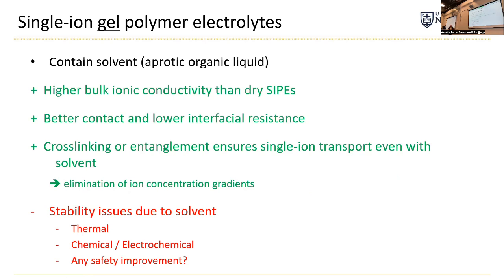Okay, so what I'll tell you more about today is our recent work on single ion conducting gel polymer electrolytes. The previous slide was about polymers where there are no liquids, it's just the plastic, and those suffer from too low ionic conductivity. We know we can improve the ionic conductivity if we add liquid, so that the lithium is solvated by liquid molecules and moves by a vehicular motion.